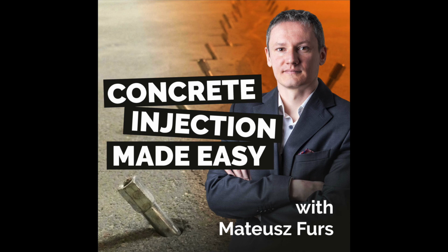Injection direction. Vertical cracks should always be injected from the bottom upwards. Make sure you see the lower beginning of the crack. It may be hidden underneath the bottom slab. If so, you need to drill the hole in the wall downward. As soon as injection resin oozes out of the adjacent packer, the first one is sealed and the injection process can be continued